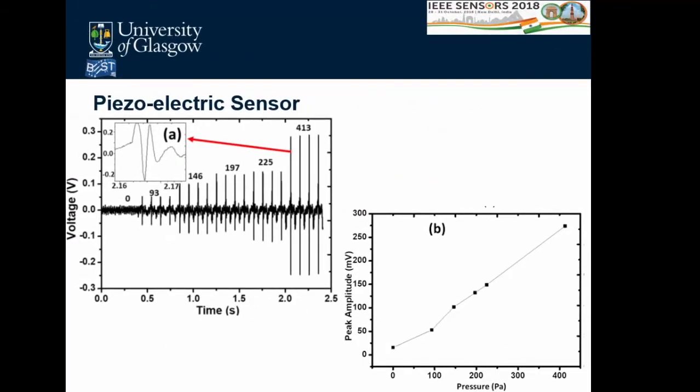The piezoelectric sensor was stimulated with a 100 Hz signal. Despite the piezoelectric stack being at the bottom of the tactile sensor, the observed response is linear, consistent with the governing equation. The sensitivity measured was 2.26% per kilopascal, demonstrating the sensor can respond to both static and dynamic stimuli.